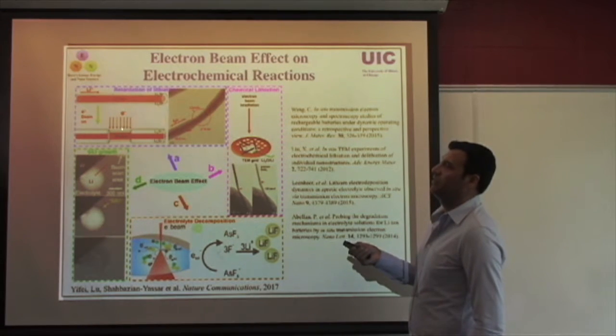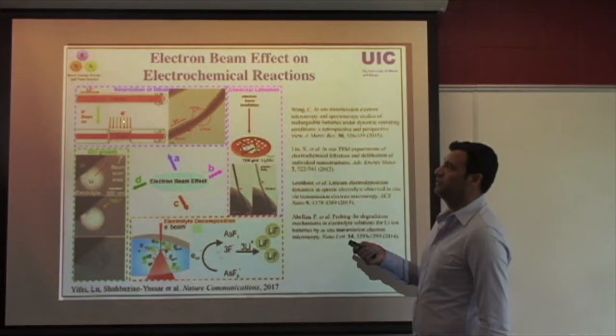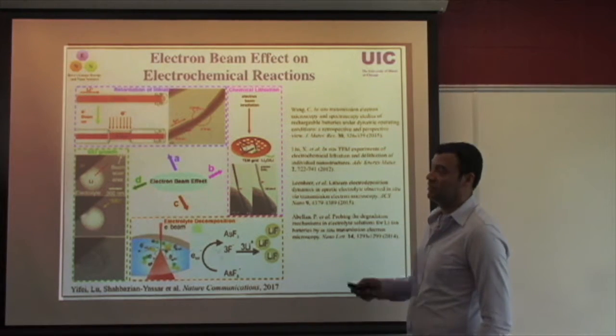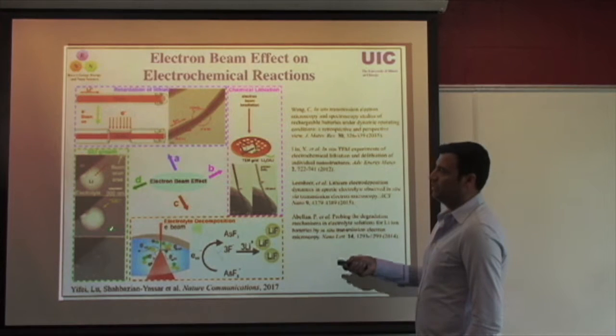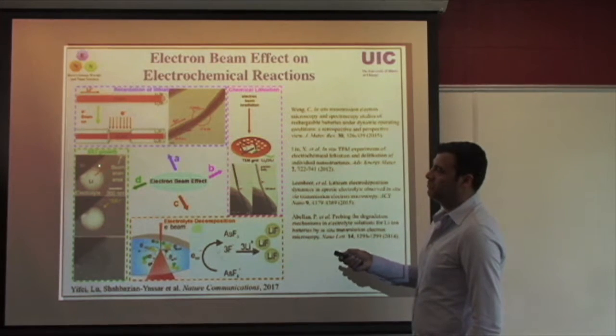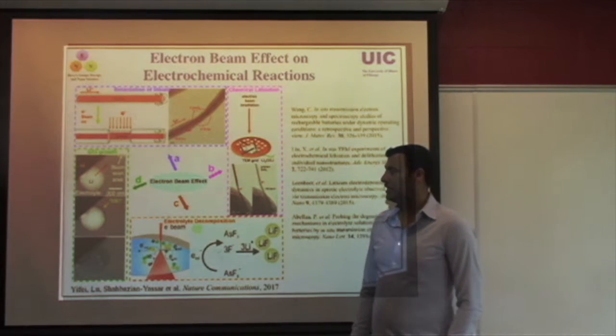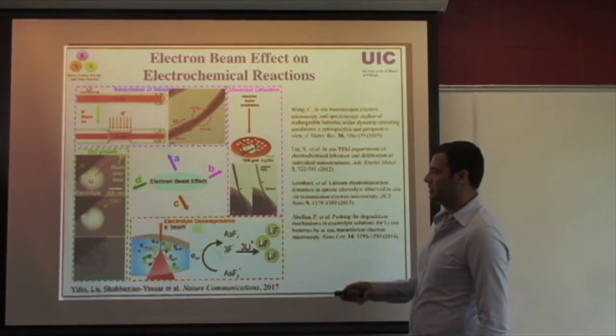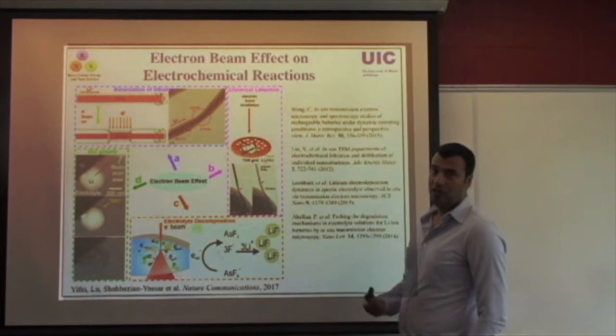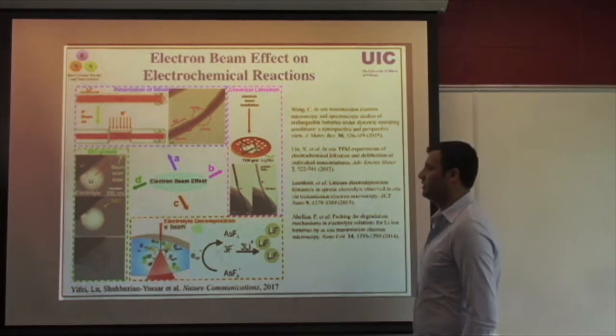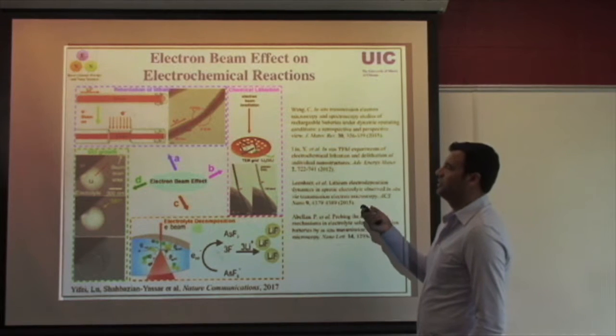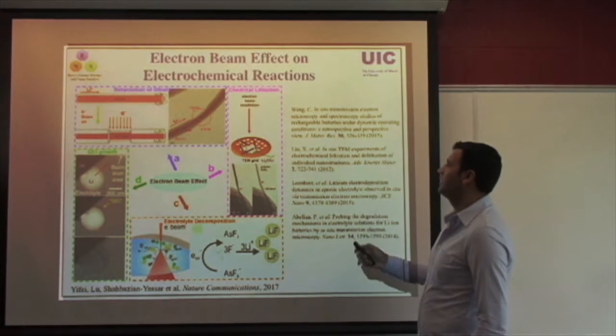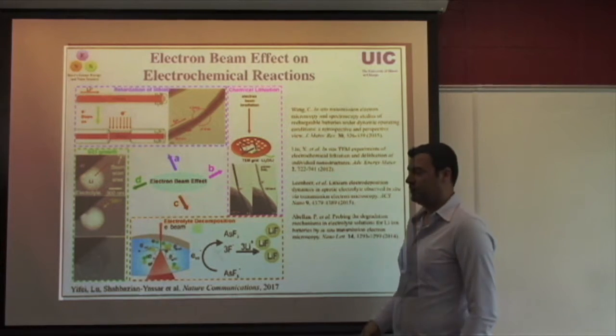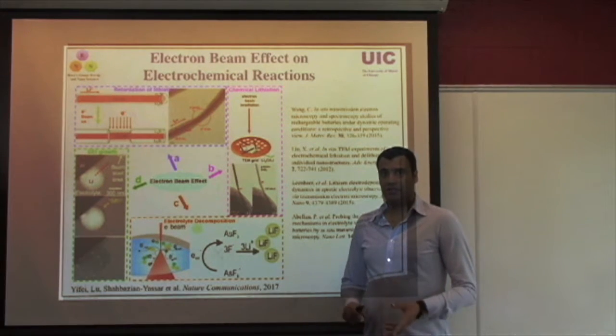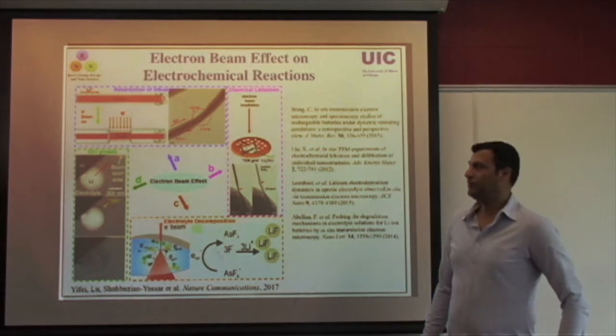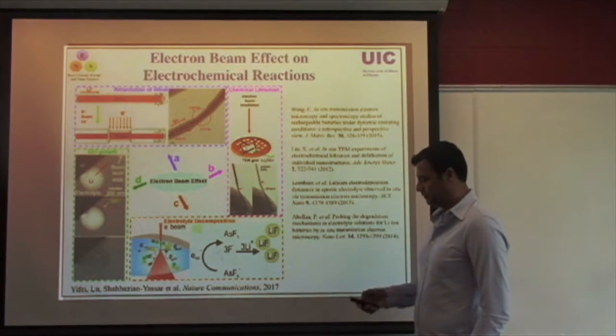As examples, people have shown that by electron beam, they could control or change the lithiation behavior in the electrodes. People have looked into electron beam effect on the formation of SEI and the change in the behavior of SEI kinetics. Some people have looked into electrolyte decomposition under the effect of electron beam, or some chemical lithiation or electrochemical lithiation associated with the electron beam effect. So there are a variety of ways that these issues have to be carefully addressed.